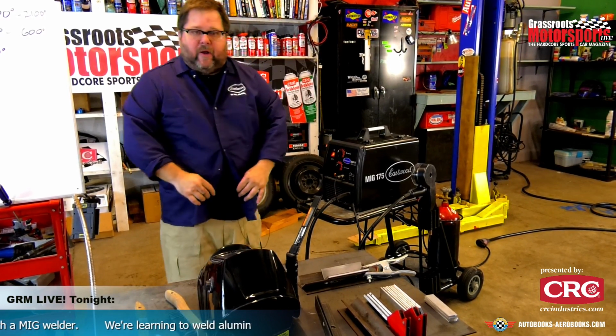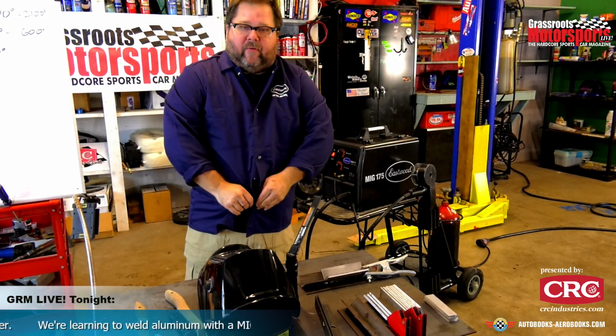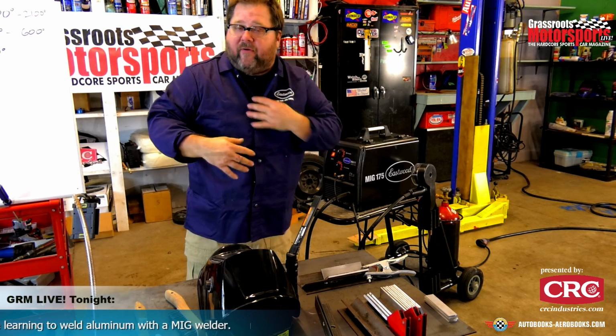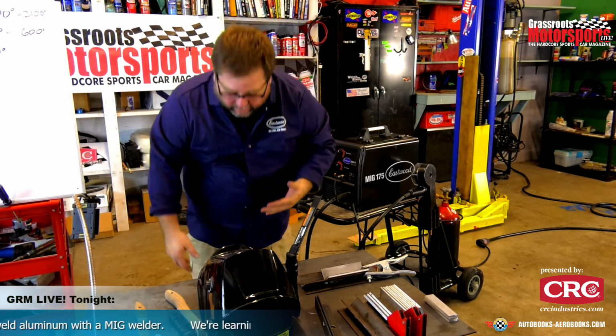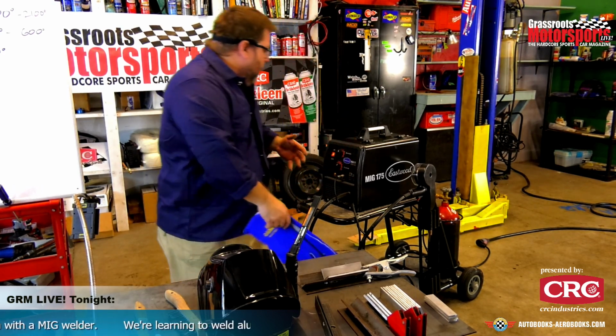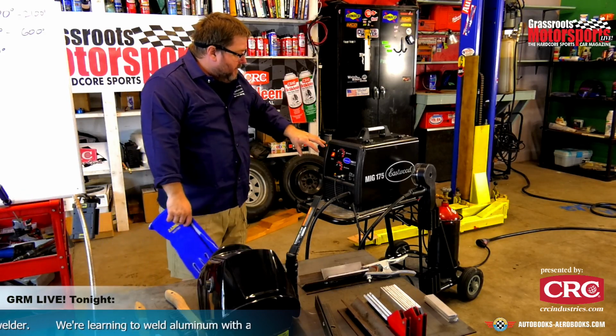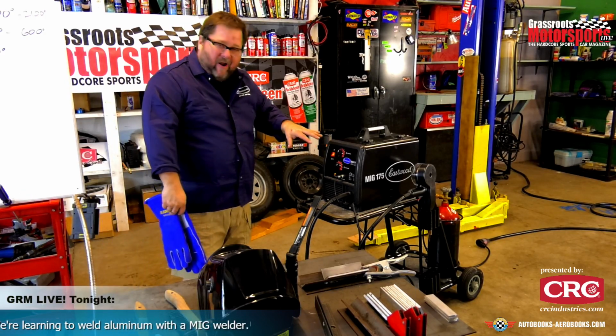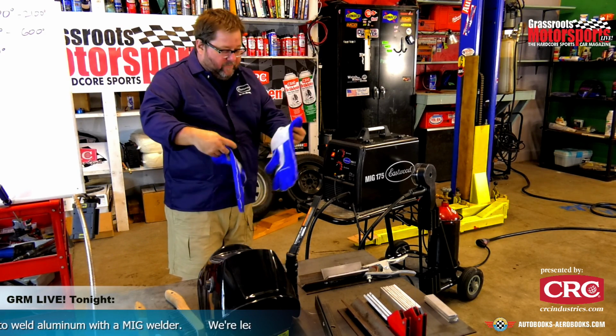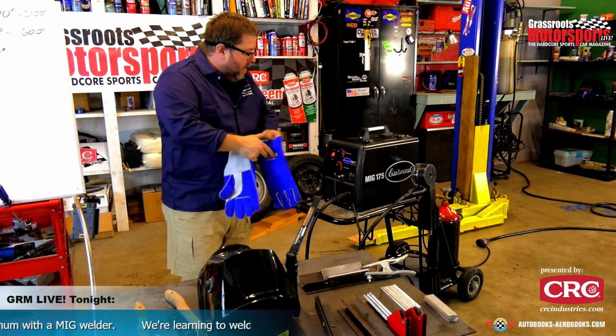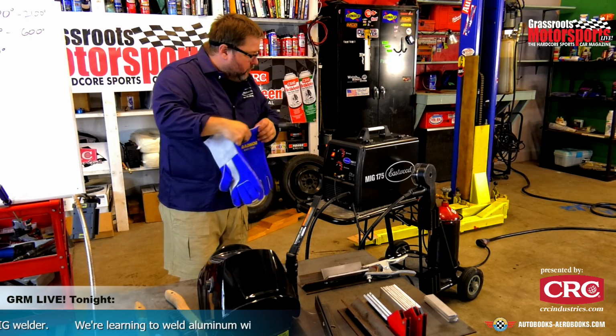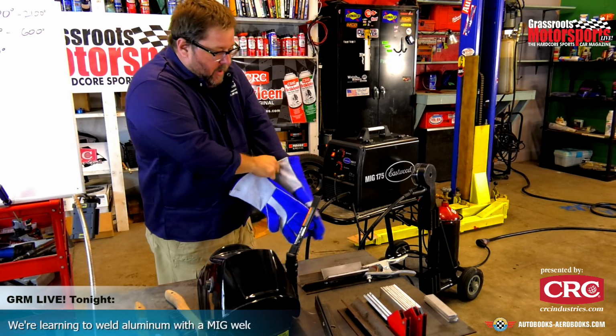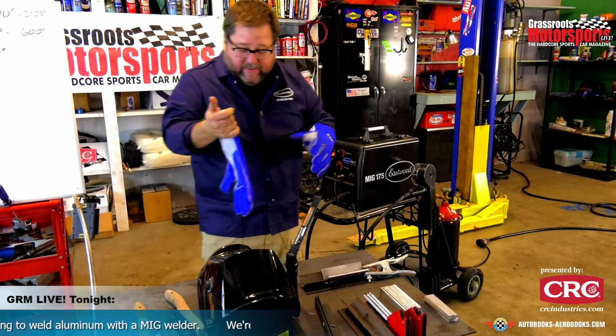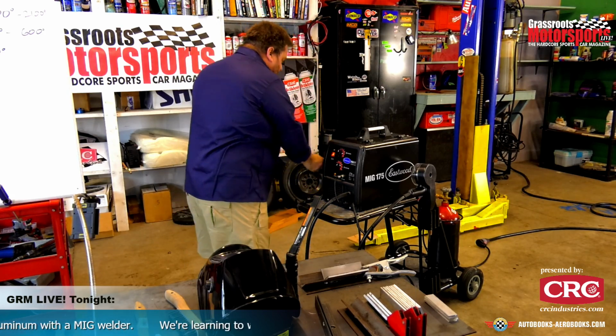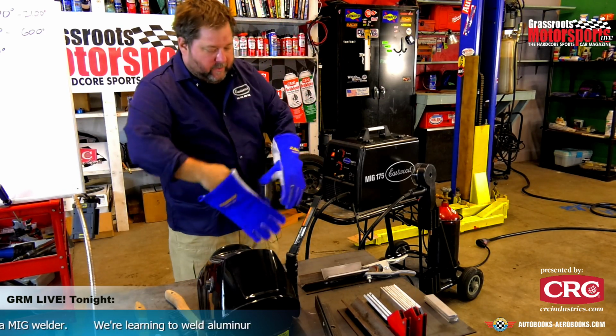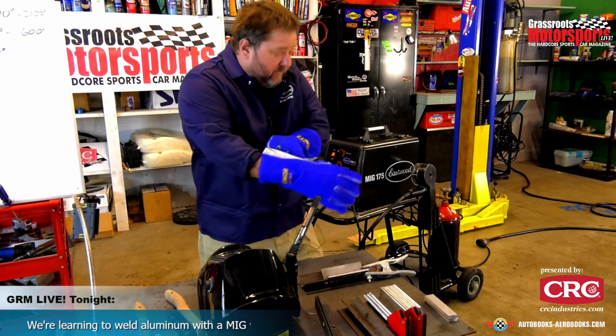I also know because the wire melts so fast and so thoroughly, my wire speed needs to be a little bit faster than it would for a similar thickness of steel. So I've got my voltage set probably about 1/2 to 2/3 of where it would be for steel, and I've got my wire speed set 20 to 30% higher than where it would be for steel, and we're just going to see how it goes. We will take a swing and see how it works.